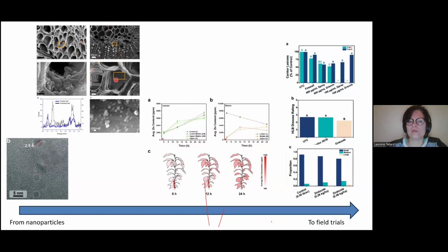So we found some vasculature where we could see the nanoparticles, and when we did elemental analysis, we could confirm that zinc is present in those chunks that we see in the plant. Then we did sectioning of the seedlings, and we did some more elemental analysis for zinc content, and we were able to map the movement of the treatment inside the plant.